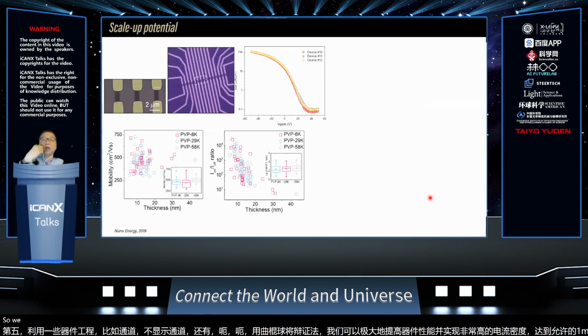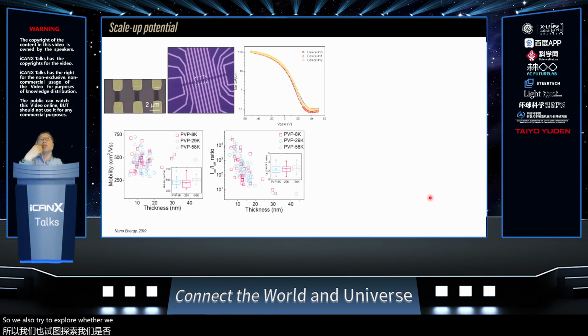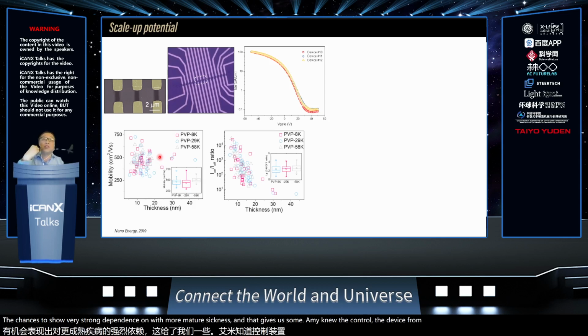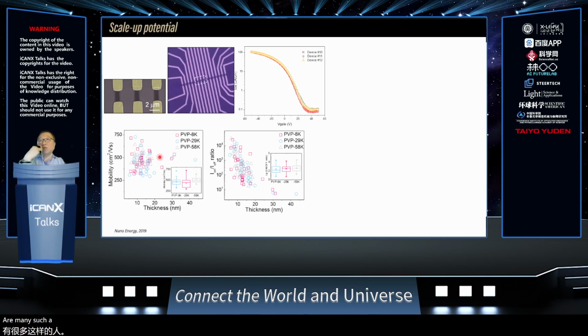We also tried to explore whether we can really scale up the production of tellurene using this method, and we probed the reliability and repeatability of these materials. It turns out that the obtained samples show very consistent performance in terms of field effect transistor devices, and the performance of the transistor shows very strong dependence on the material thickness. That gives us an avenue to control the device properties through the manufacturing process. Before that, we need to understand the process-structure-property relation.